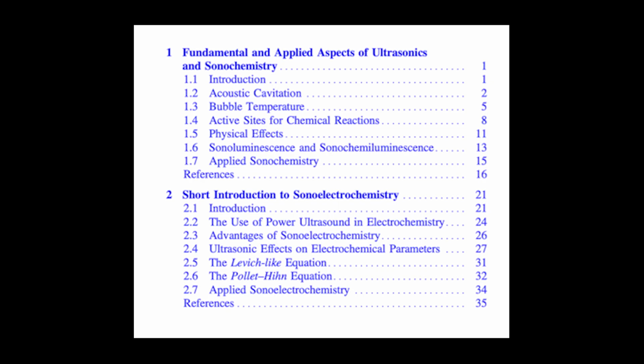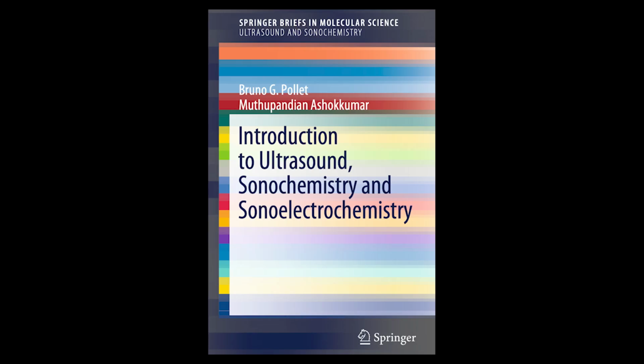What's the other reason? The other, perhaps more common explanation goes back to the surface cleaning and activation. By constantly removing oxides or adsorbed inhibitors, the ultrasound is essentially presenting a more active, cleaner electrode surface to the reactants. This cleaner surface might allow the electron transfer to happen at a potential closer to its true thermodynamic value, thus shifting E1/2.